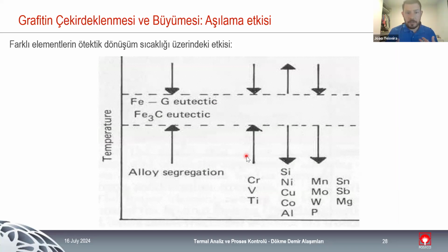And this picture is just to illustrate that, since we are adding a lot of different elements to the melt, these different elements are going to have some role at the end. And it is really important to understand how the different elements are going to impact the solidification and the overall quality of the cast. And you can see here, these dot lines are the stable and the metastable temperatures. So these are the temperatures where the transformation of carbon into graphite happens. And you can see, for example, that silicon improves this window of transformation. But for example, chromium, vanadium, titanium, so elements that have a lot of affinity with carbon, they close this window. So if you have a base metal with a lot of chromium, titanium, we have less time for the carbon to transform into graphite, and it could have a lot of carbides.